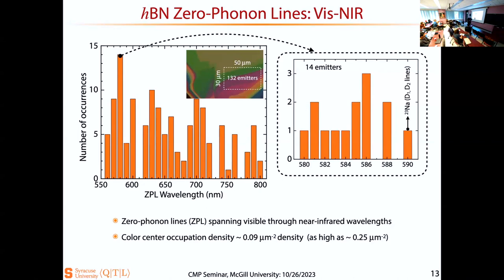There was a recent paper in which, in a CVD sample, they first found out where the color centers are, and then they grew another sample in a carbon-rich environment. And they did see that the population of the color centers around 585 went down. So that was a good indication that maybe around 585, it is a carbon-related effect. That is only one of the papers I've seen suggesting maybe this is carbon. But the jury is out on what that was. And this was one of the fundamental questions.